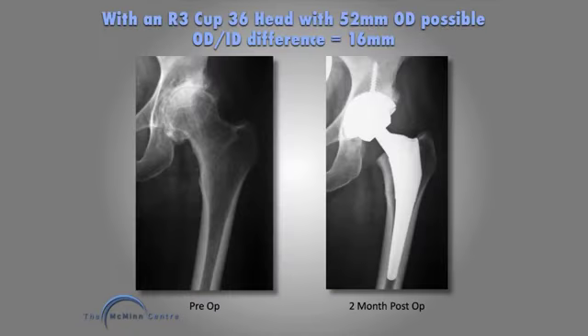The first problem, however, is size limitation. So when I use a 36 head with a 52 millimeter OD cup, then the best I can get is a 16 millimeter outer diameter to inner diameter articulation. And that just reflects the fact that you need a finite thickness for the metal shell, and you need a finite thickness for the polyethylene. Now, for comparison, the Birmingham hip resurfacing has a 6 millimeter outer diameter to inner diameter difference.